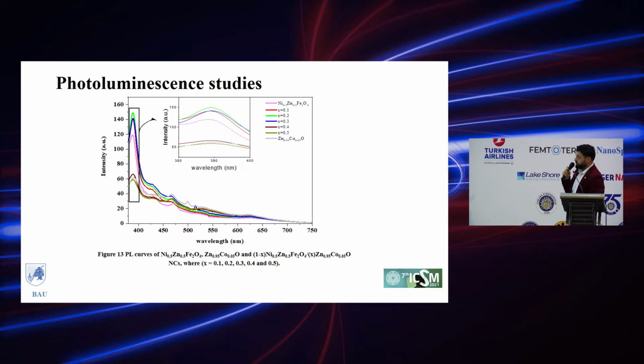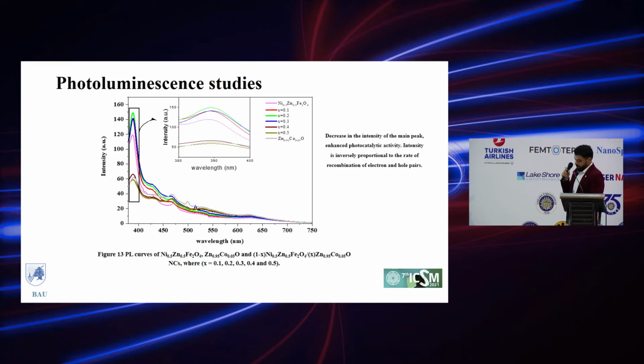The photoluminescence studies, which are very important in photocatalytic activity, were performed also. As we can see, we have a violet near band gap emission, and we have deep level emissions for all samples. We also found a decrease in the intensity of the main peak, and this decrease is favorable for photocatalytic activity because, as you know, intensity is proportional to the rate of recombination of electron and hole pairs.